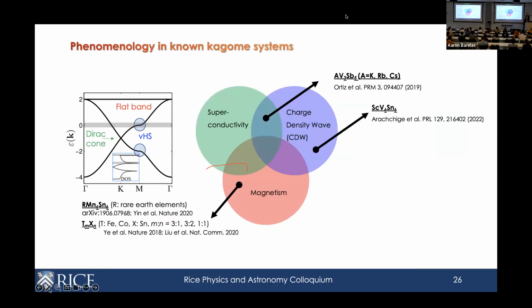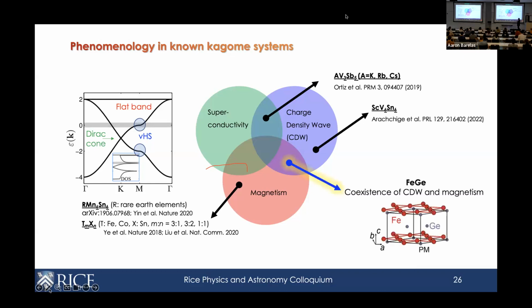Maybe it's not so hard to understand why they are so divided, because if you look at this picture, the Fermi level is either near the Van Hove or near the flat band, but it's very hard to engineer one where it's near both, right? This is why it was very surprising, actually, 2 years ago, that Peng Cheng's group discovered a compound that exhibits both a charge density wave and a magnetic order in this overlapping region. And this is a story I'm going to tell you about because we work on this together.